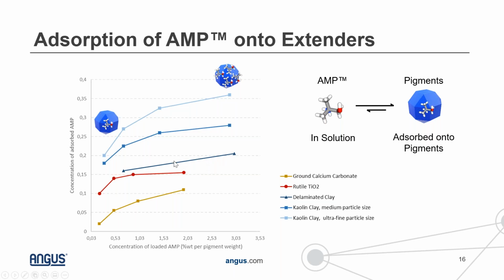And so what we see in all of these cases is an adsorption of AMP onto the extender particle surface. So for example, if you look at 1% AMP on pigment weight in your slurry, we're seeing about 10% of that is found on the surface of calcium carbonate, 15% on TiO2, and it increases from there when you start to look at some of the clays. And so this, again, is a very typical response for a material that has a very strong adsorption to particle surfaces.